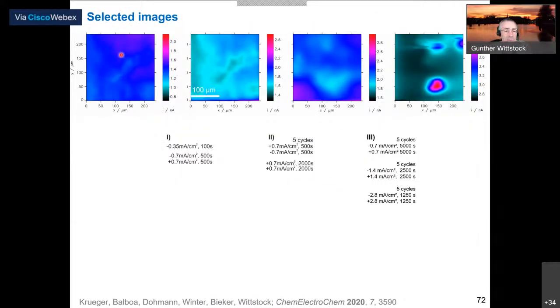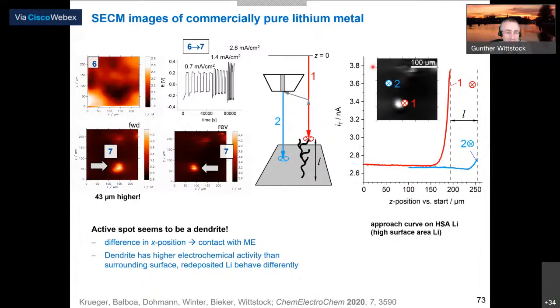So here you see it again. Initially not too much change, then a little bit more change. And finally, we form isolated regions with very high current density. So if we then want to investigate those more closely, we can position the electrode over an area far away from such a spot and directly on top. Then we make an approach curve and we stop the approach curve.